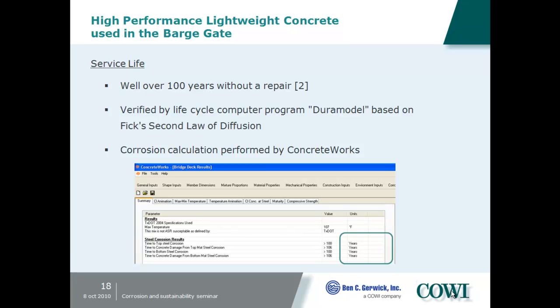And they wouldn't accept impressed current cathodic protection at the end. We have used passive anodic protection or anodes, as Birgit showed. We used that on the Diablo Canyon intake structure, where we put in zinc strips into the concrete, and that worked well there. But the contractor didn't want to do that here, so our options were getting more and more limited. So we did use these as it was showing. She was showing 75-year service life, and then she had to do something else after that. And so we didn't have all those options. So for whatever it was, we used this one model, which uses Fick's law for getting the chloride in and then predicting a certain amount of life.